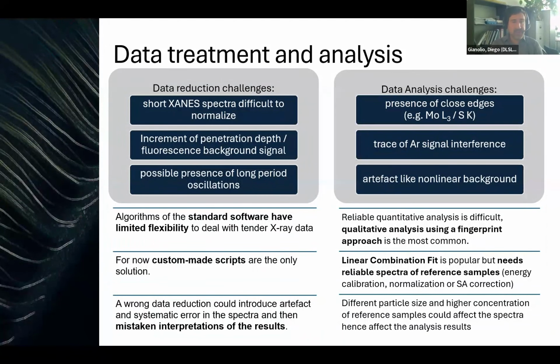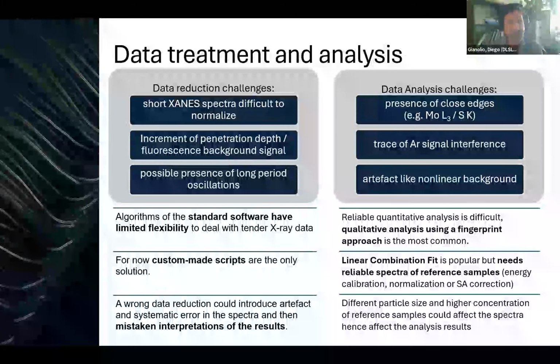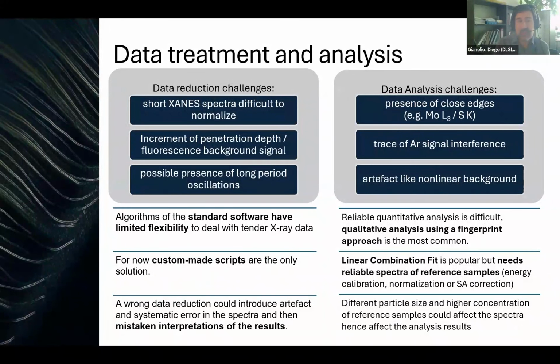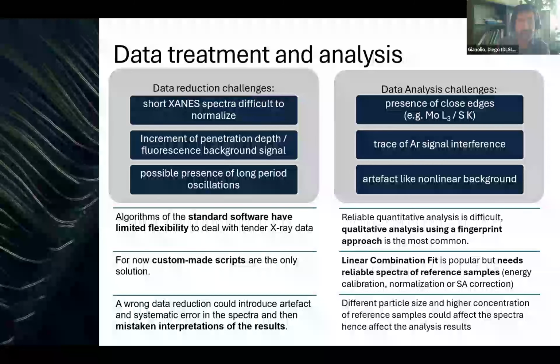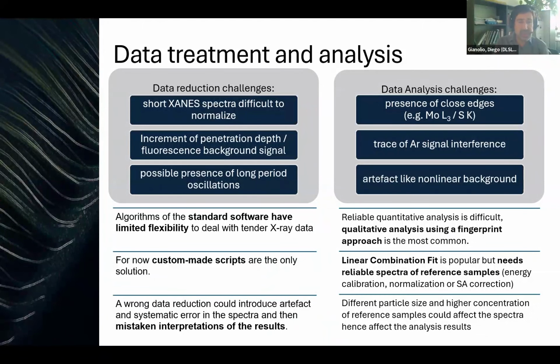And once the data have been collected, the data treatment and analysis also present some unique challenges. One that I mentioned before is that normally the spectra are quite short, so it is difficult to do normalization. The other is that because of the short penetration depth, while scanning in energy, you could also have a change in the penetration depth as a function of energy, and this could affect the background. And there is also the possibility of the presence of some sort of long period oscillations.